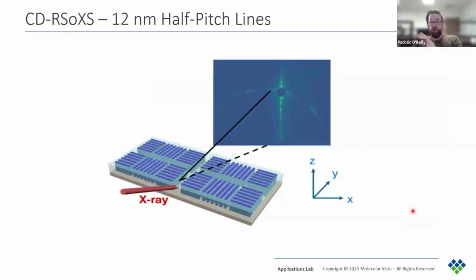So the other tool that was used for this study was CD-RSoXS. So CD-RSoXS offers statistical measurements over a larger sample area, and it captures the ensemble averaged periodic structural details, so topographical structure, but it also has sensitivity to specific chemical environments as well.